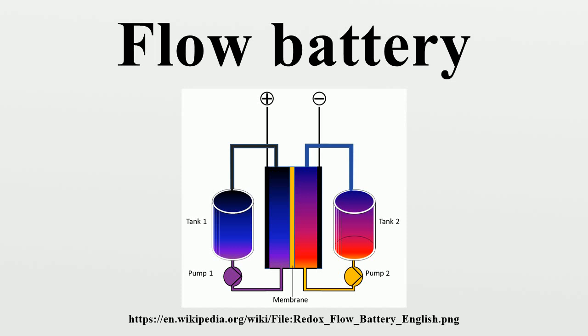Cycling showed greater than 99% storage capacity retention per cycle. Volumetric energy density was over 50 watt-hours per liter, and specific energy density over 50 watt-hours per kilogram. The organic anthraquinone species can be synthesized from inexpensive commodity chemicals. This organic approach permits tuning of the reduction potential and solubility by adding functional groups. Adding 2 hydroxy groups to AQDS increases the open circuit potential of the cell by 11%.